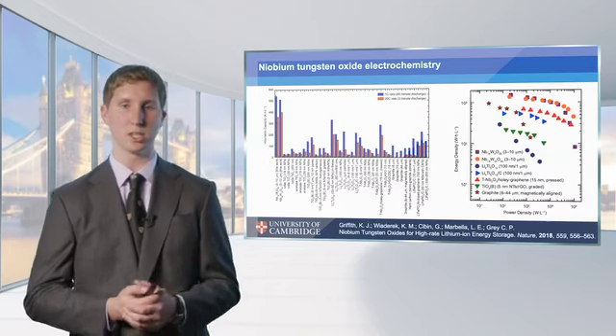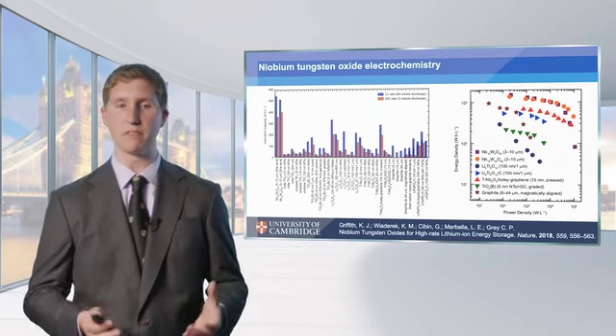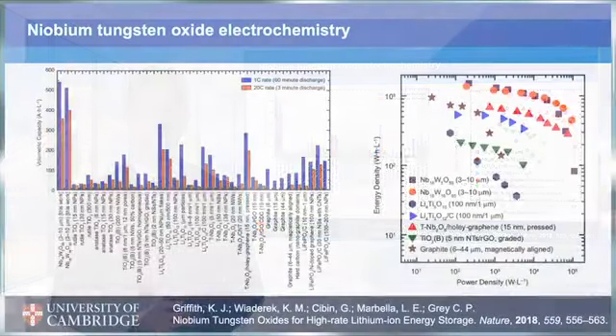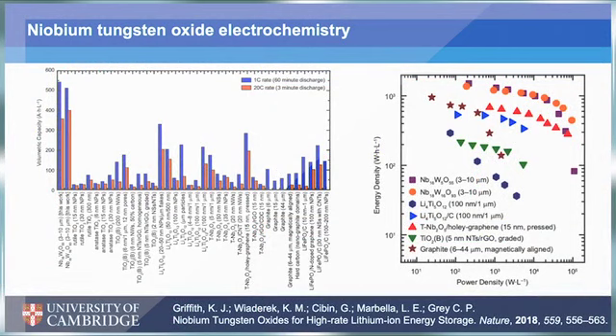And so comparing that to everything else out there, even very small nanostructures of things like TiO2, different versions of LTO, different hierarchical complexes with carbon nanostructures and porosity, all of these things, these niobium tungsten oxides compare very favorably. They have a very high volumetric energy density, thanks not only to their inherent crystallographic density, but then also this microstructural density where we're using bulk dense particles. And so what that means is we can pack a lot in a small space, and for volume-constrained applications, which applies to many, many things.